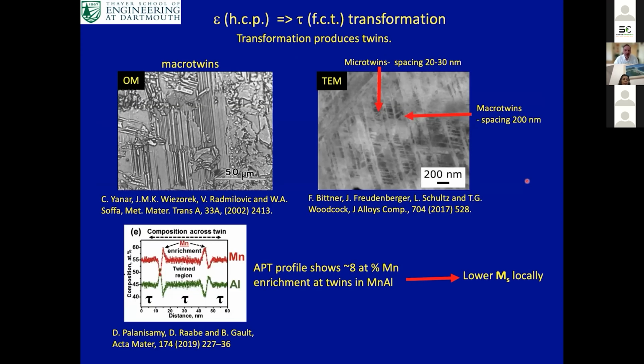Now, the interesting thing about the transformation from the high temperature phase to the tau phase we're interested in, it actually produces lots of defects. And it's not quite clear what all of those defects do. So the first type of those is these macro twins here that you can see in this optical micrograph. And in addition to that, you get micro twins seen in this transmission electron micrograph, these very fine features here, the micro twins in the material, from two different pieces of work here.